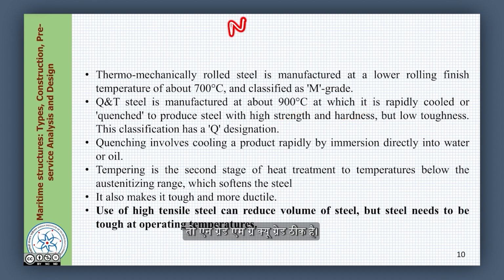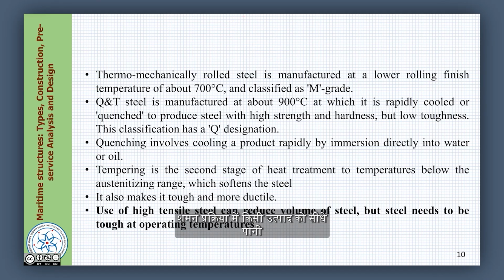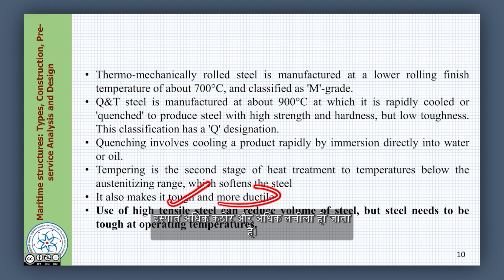So, N grade, M grade, Q grade. Okay? Quenching involves cooling a product rapidly by immersing it directly into water or oil. Tempering is the next stage of heat treatment, to temperatures below the austenite range, which softens the steel. So, when you do quenching and tempering both, then it makes the steel tougher and more ductile.